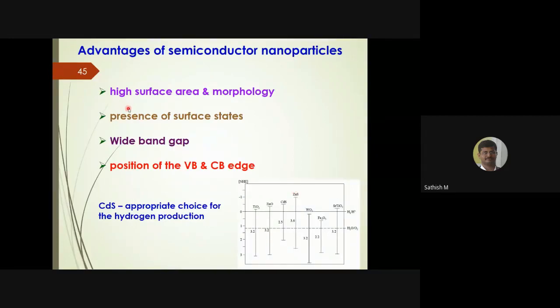Here you could see, most of the semiconductors have very high surface area. TiO2 is perfect, zinc oxide is also perfect, but the problem is the 3.2 electron volt band gap. Because of this, we cannot use it in visible light. Okay. The cadmium sulfide looks good. It comes under the orange category, that is 2.5 electron volt. It's well within the visible region. Whereas if you go for zinc sulfide or WO3, Fe2O3, strontium titanate, all have their own advantages and disadvantages.